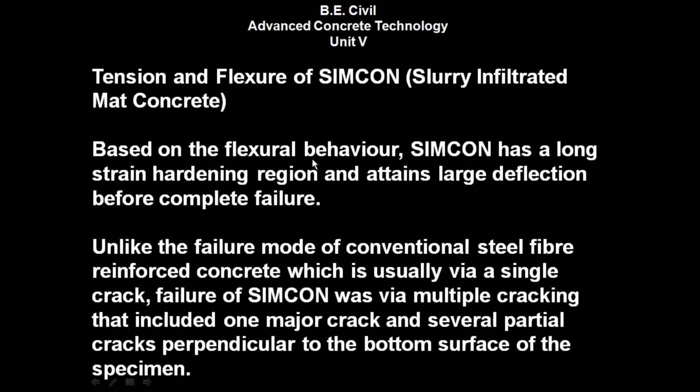Based on the flexural behavior, SIMCON, that is slurry infiltrated mat concrete, has a long strain hardening region and attains large deflection before complete failure. Unlike the failure mode of conventional steel fiber reinforced concrete, which is usually via a single crack, failure of SIMCON was via multiple cracking that included one major crack and several partial cracks perpendicular to the bottom surface of the specimen.